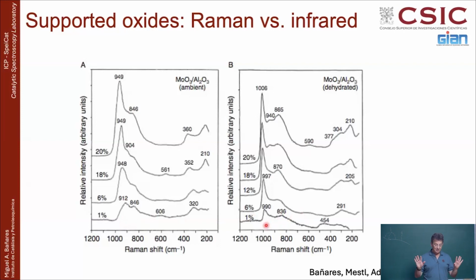So the main difference, which is something that people did not really know, I'm talking about 20, 30 years ago, is that ambient conditions really have an effect on supported oxides, because supported molybdenum, vanadium, chromium, tungsten, all these elements which are very important for oxidation catalysis, are sensitive to ambient moisture. They get hydrolyzed, they get solvated, they go totally hydrated. And then you see that they look different, and you can tell what is happening here.